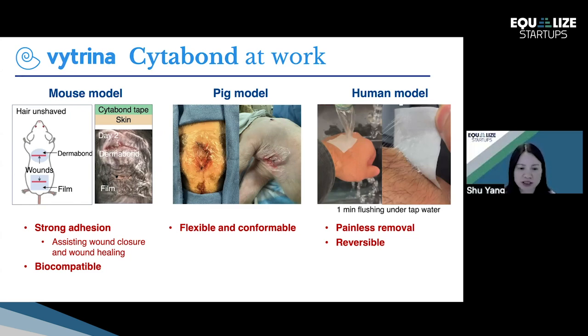As you can see from these images, we show strong adhesion compared to Dermabond to close the wound. The material is biocompatible, and on the pig skin you can see beautiful wrinkles because our film is very compliant and conformable, while also having strong adhesion. By simply wetting with water, the film softens and becomes compliant to irregular surfaces. When dried, it shows strong adhesion. And when we want to remove it, we expose it to water again.